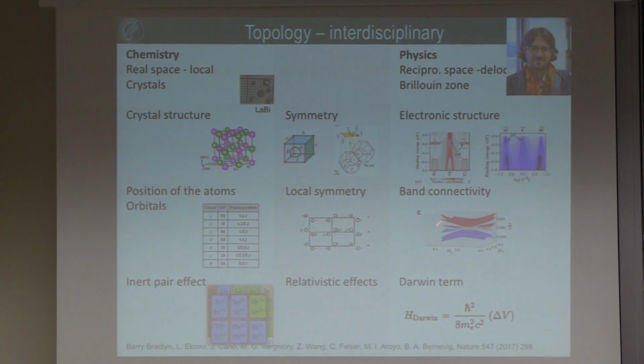I told him, look, if you want to have an 8-fold degeneration in the reciprocal space, you have to have the analog in the real space, so you have to have atoms in a cubic lattice, for example, sitting on the Wyckoff position, and so on. So this was a first connection, and it's clear nowadays. If you give me an electronic structure, it's possible more or less in a kind of inverse design to think about the crystal structure.